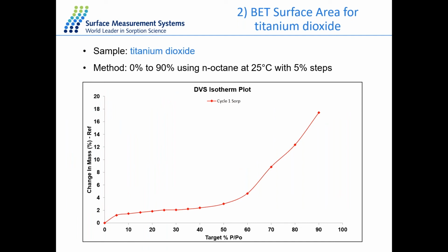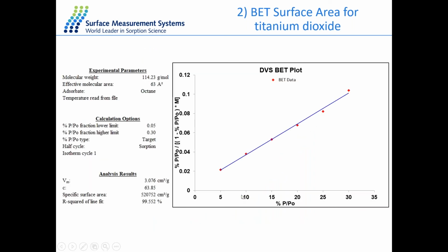We also perform the octane sorption from 0 to 90% RH with 5% intervals in the BET range, and then 10% intervals just to get a full isotherm. We also use the points in the BET range to calculate the surface area with the same equation as before. We get the monolayer volume, the sorption constant, and the surface area for this TiO2 sample, which is about 52 square meter per gram, with quite linear regression as well.